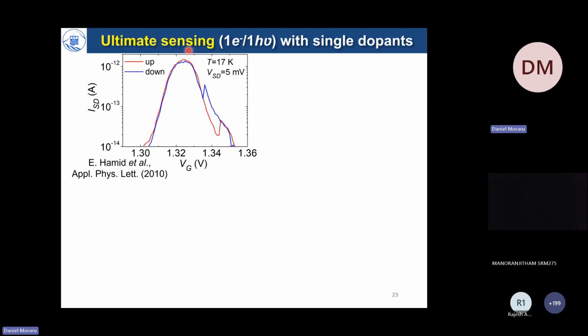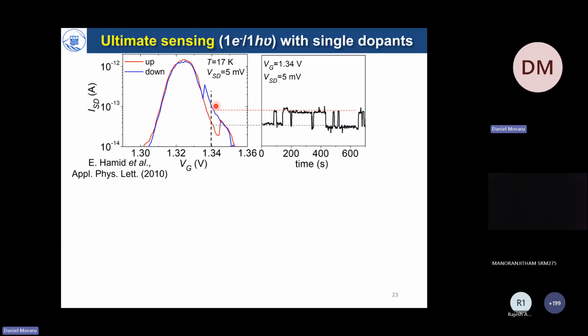And we think that ultimate sensing can be one of those. Let's take one example from this Applied Physics Letters publication. We actually took one of its peaks and measured it upwards and then downwards and observed that it contains, in some cases, a hysteresis of current between upward and downward sweep. And if you measure the time dependence inside this hysteresis, it switches between mainly two levels. And that switching is actually a detection using single electron tunneling through one dopant of a charge state of another dopant working as a trap. So this could be developed or converted into a memory concept which utilizes a single atom as a sensor and a single atom as a memory node.